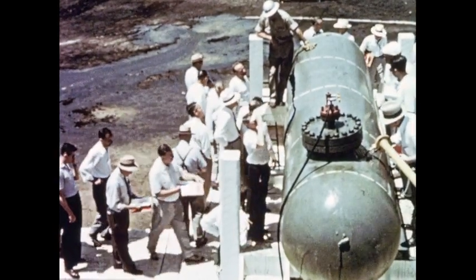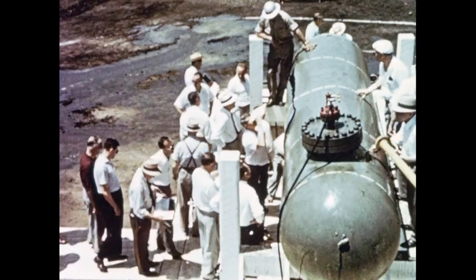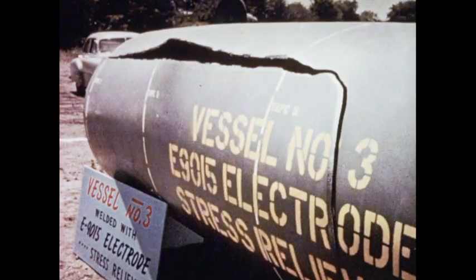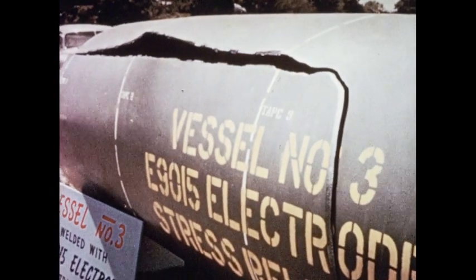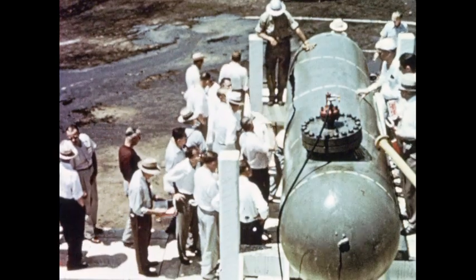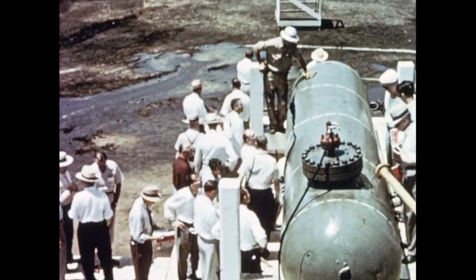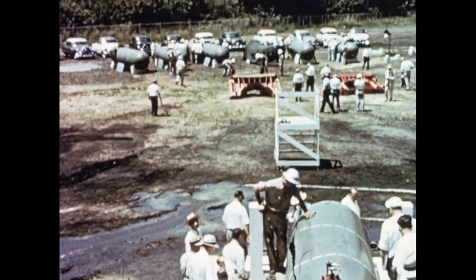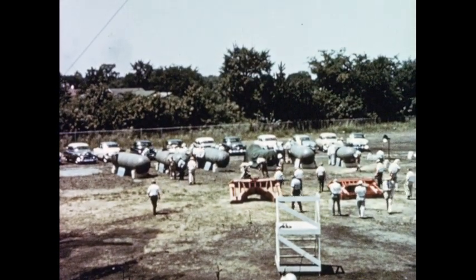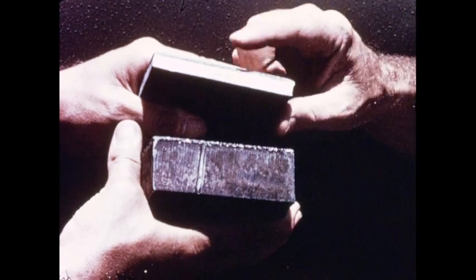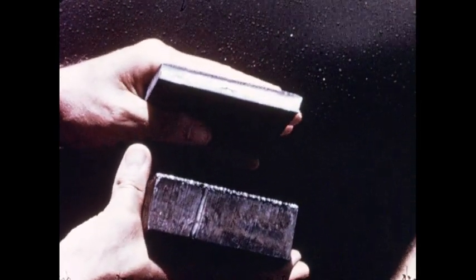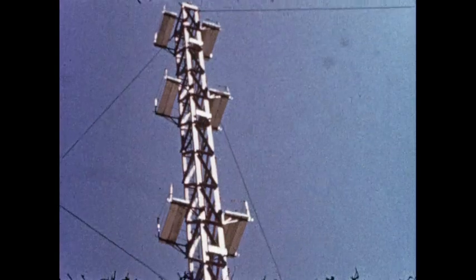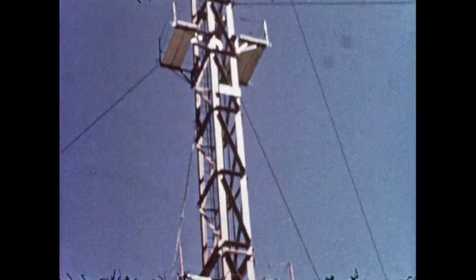After such a burst, even at this frigid temperature, T1 showed no evidence of brittleness or shattering. Note the simple tear. Incredible ductility for an alloy steel having such a high strength level. Other vessels subjected to similar burst tests ruptured at about the same pressure, demonstrating the same remarkable degree of toughness. All this with a half-inch plate of T1. Had carbon steel been used, the plates would have had to be 3 times as thick to withstand that much pressure.